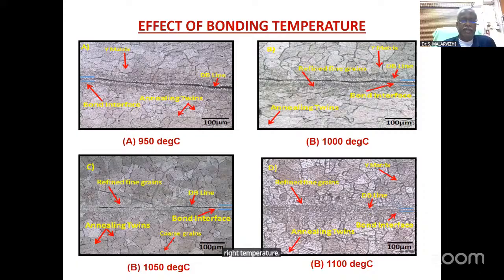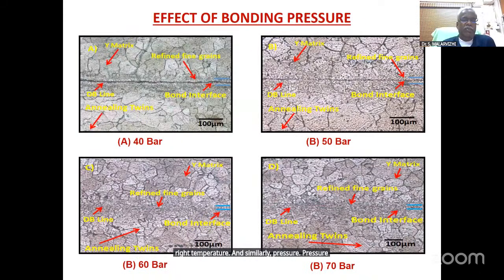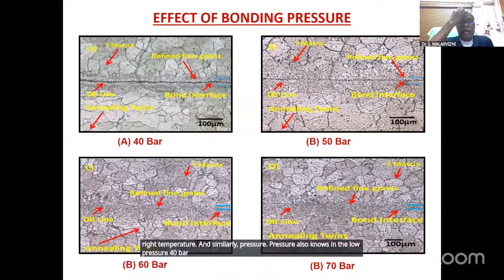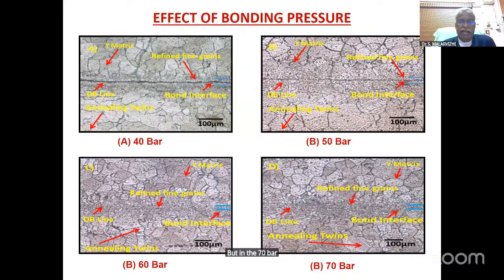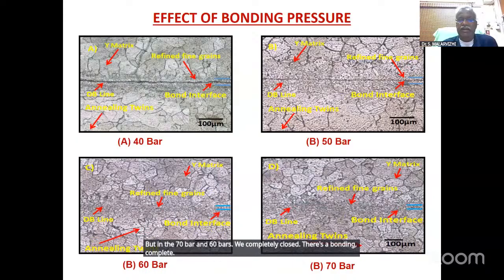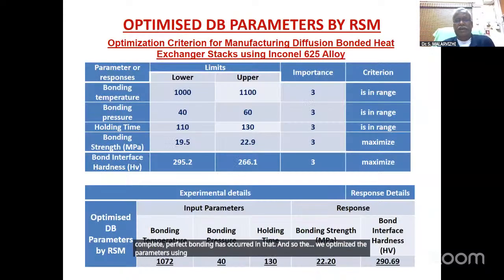And similarly, pressure also. At the low pressure of 40 bar, you see that there is still an air gap between the top plate and the bottom plate. But at 70 bar and 60 bar, it is completely closed, and complete perfect bonding has occurred. So we optimized the parameters using RSM and also compared with the experimental results.